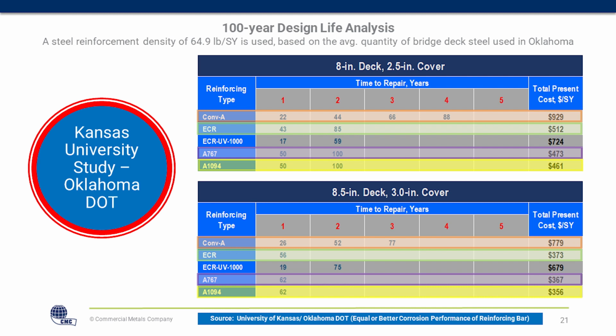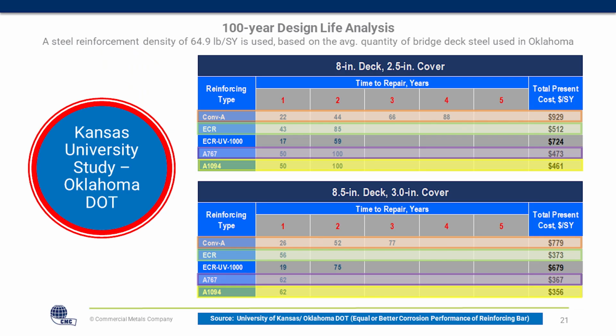And so with conventional on the 3-inch cover, they're estimating that at year 100 you would have 3 repairs, and the cost would be just south of $800, just north of $900 on the 2.5-inch deck, and you'd have 4 repairs. This is the epoxy coated material, and so you're showing 2 repairs with a cost of just north of $500. And whenever you have an extra 1/2 inch of cover, that is reduced down to 1 repair with a cost of just south of $400.